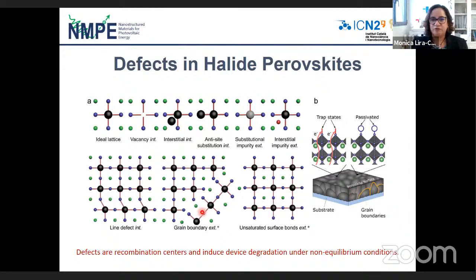You can find these defects when you have a line defect, for example. You can have a grain boundary—this is a grain boundary here. And then you can see that the stoichiometry of the halide perovskite is not what we are looking for, and that's where we have some defects.